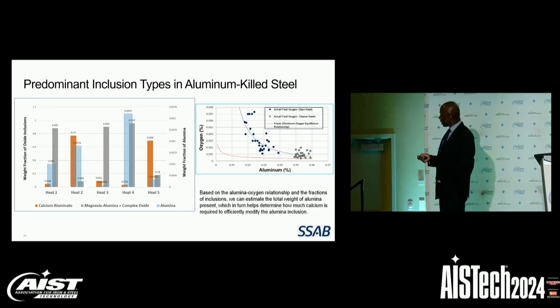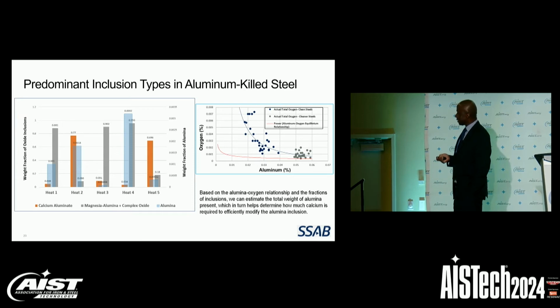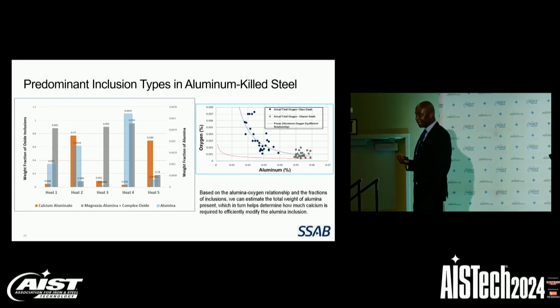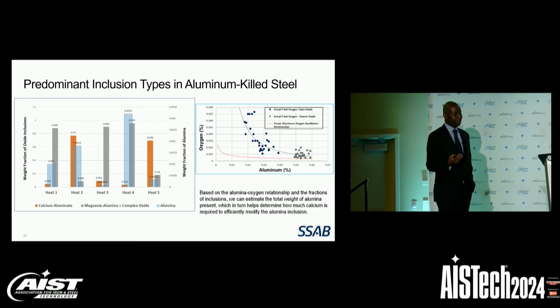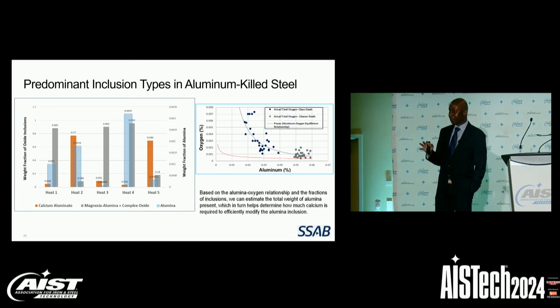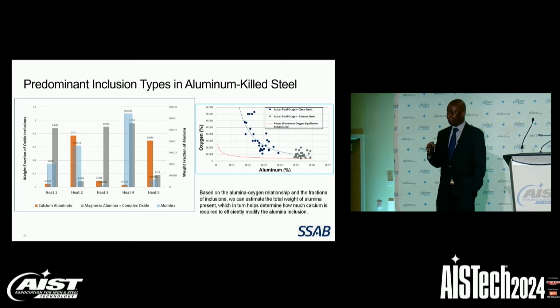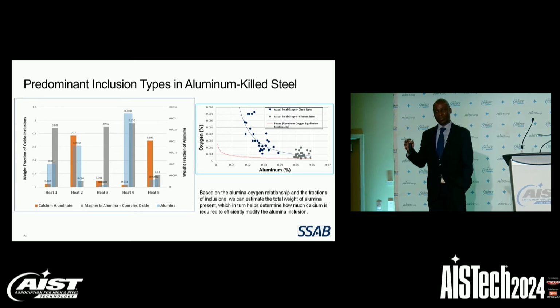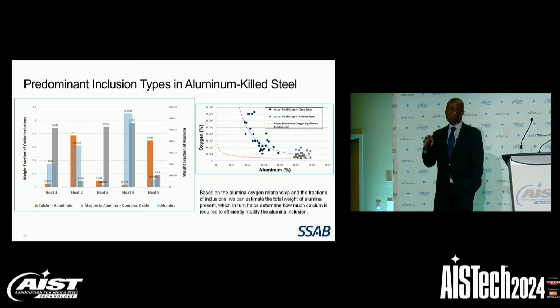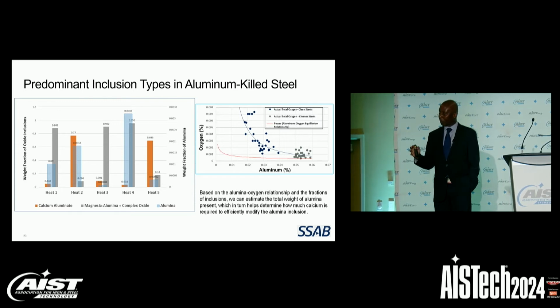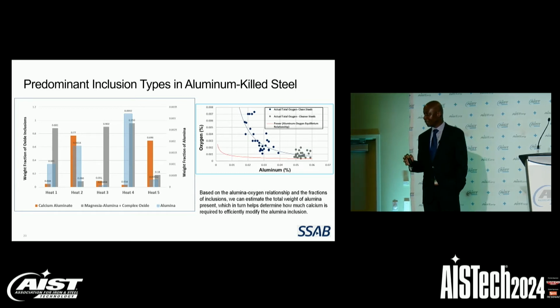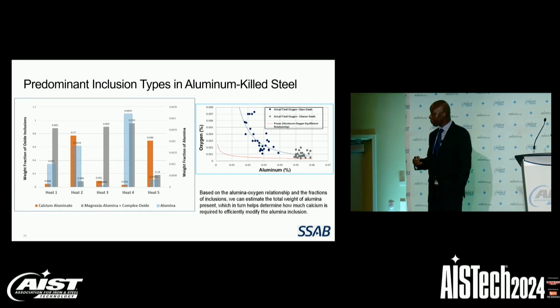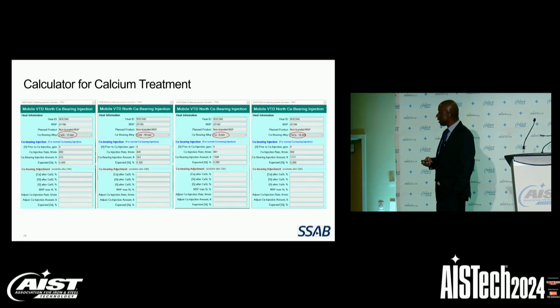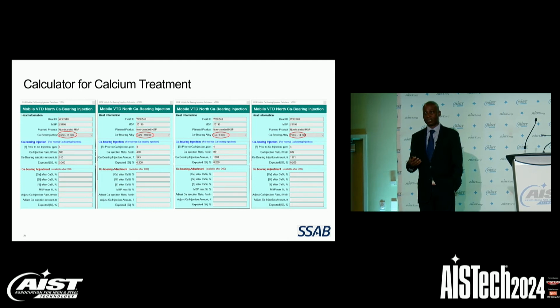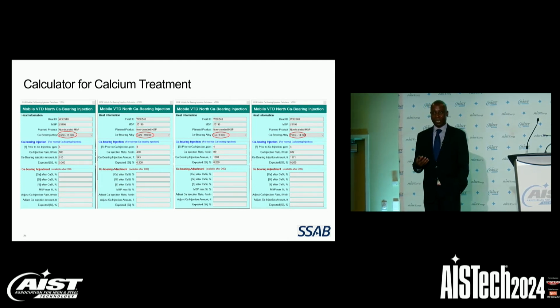However, we found that, with increasing aluminum in the steel, the oxygen potential tends to decline. So using this relationship, we can actually calculate how much calcium is required. You remember that 10 micron size inclusions don't float out quickly. Well, we can determine how much calcium to add to modify those residual inclusions, to make sure that they don't result in operational problems or cause negative impact on the mechanical properties. But if we also know the sulfur content of the steel, we can calculate how much calcium is required to completely modify the oxide and the sulfide inclusions.